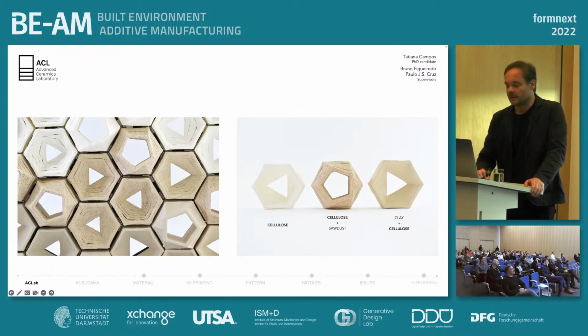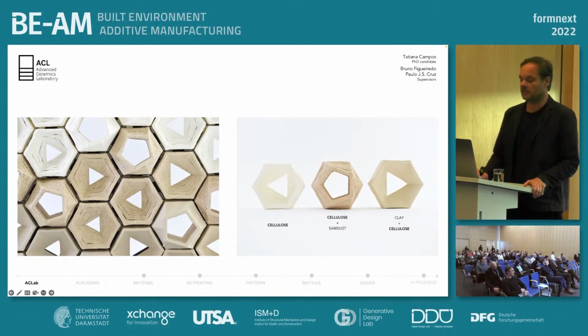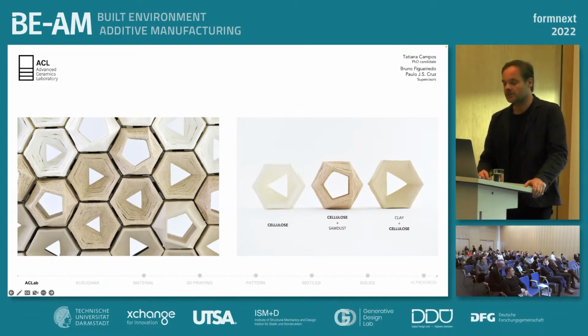As a proof of concept, we manufactured a wall made of blocks with 3 types of materials or mixtures. In the upper part, we are using only a cellulose-based mixture with starch. In the second row of blocks, we mix the cellulose with sawdust, waste from wood material. And at the bottom, we try to mix the cellulose starch with clay.